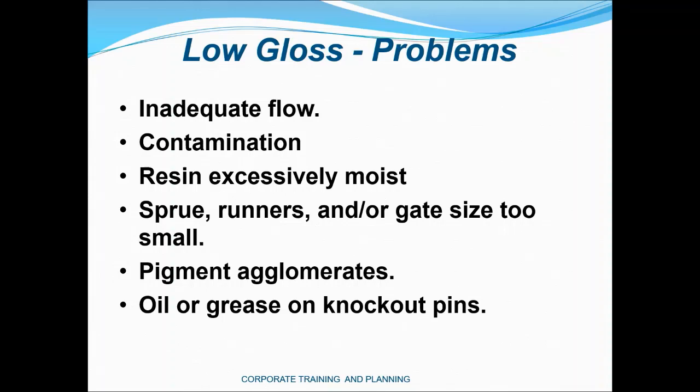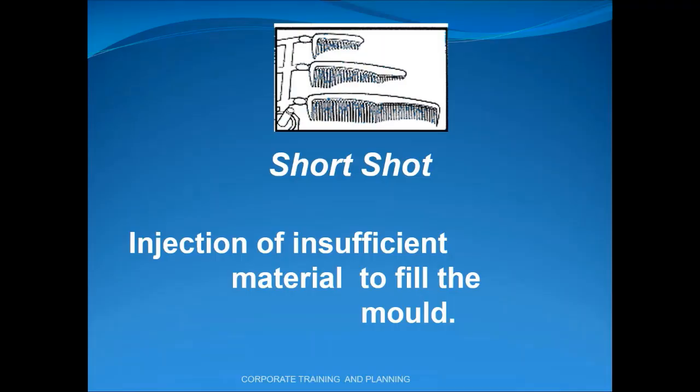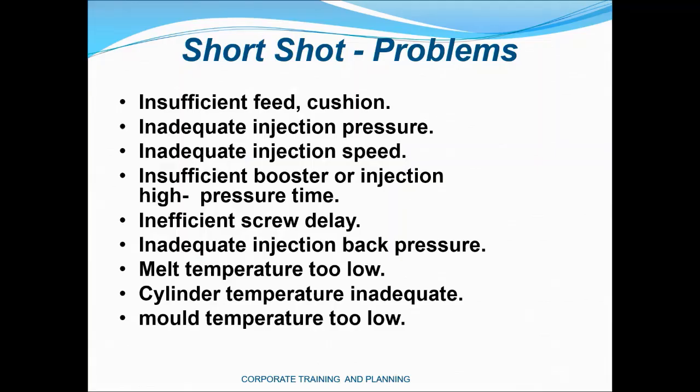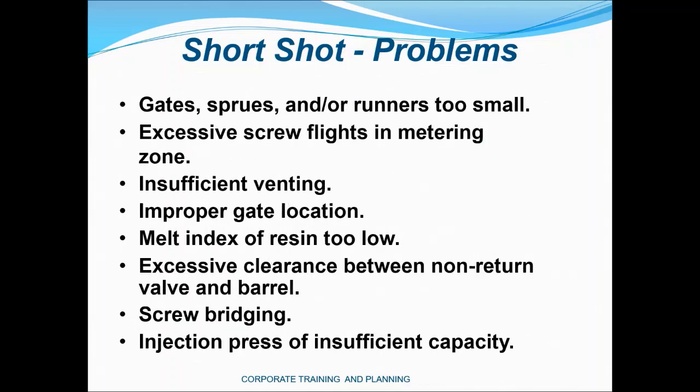Short shot is injection of insufficient material to fill the mold. Short shot problem: insufficient feed cushion, inadequate injection pressure, insufficient venting, injection press insufficiently capable.